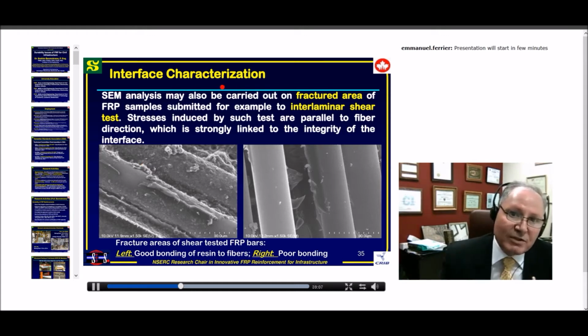So I would strongly encourage you to do that also on as-received material, looking at the microstructure and whether there is any defect or not. Also, about the interface characterization, you can do it before testing and also after testing, for example on the fractured area, and this gives you a very good idea about the interface. As you can see here on the left, on the fractured area, the resin is still bonded to the fibers, which means a very good interface, showing the integrity of the interface. But on the right, you can see smooth fibers, and all the resin was removed because the failure was at the interface, which is really poor bonding.